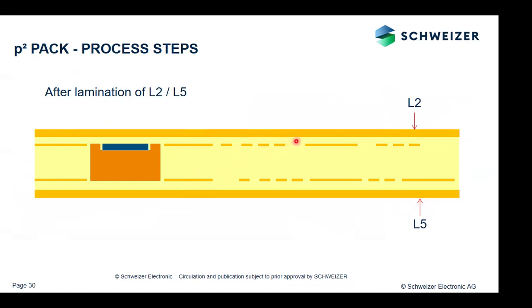So a pre-preg is a pre-impregnated glass weave. So you have epoxy resin in a B stage, so-called B stage. So it's dried and pre-cured. And in the lamination process, you bring pressure and temperature to this construction. With the temperature, you get a lower viscosity of the resin. You fill out all the empty voids. And after the flow of the resin, you get into a curing stage where you cure the whole construction. And after this lamination process, the component is fixed inside the PCB, but it doesn't still have any contacts.